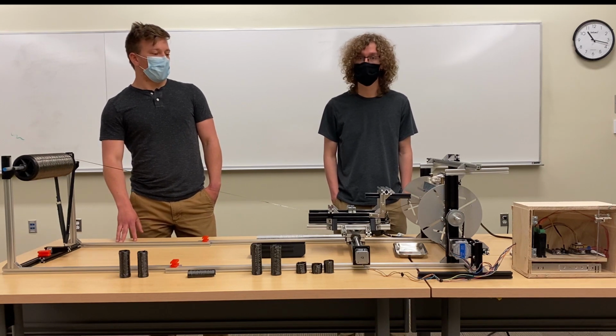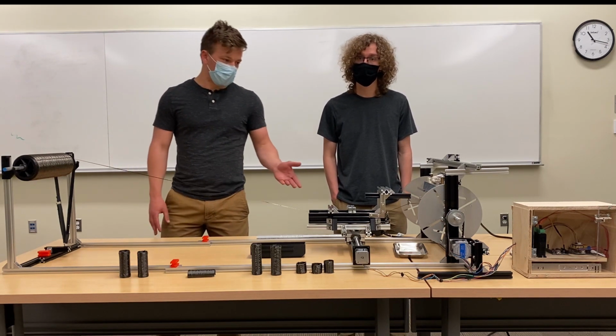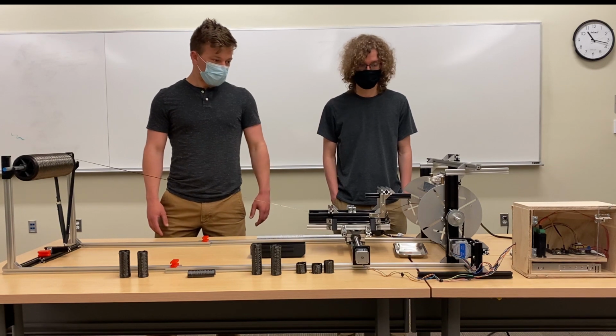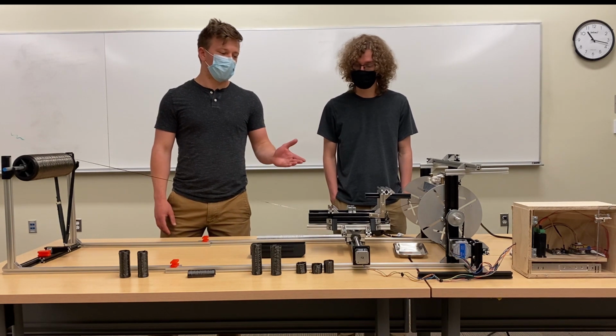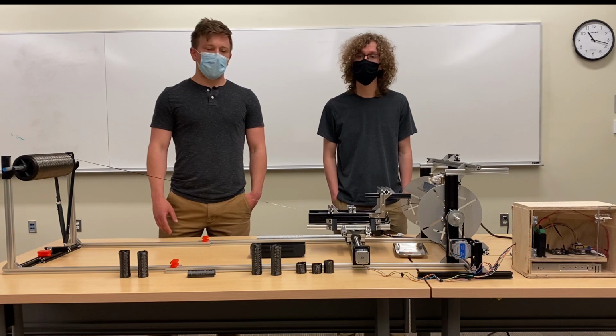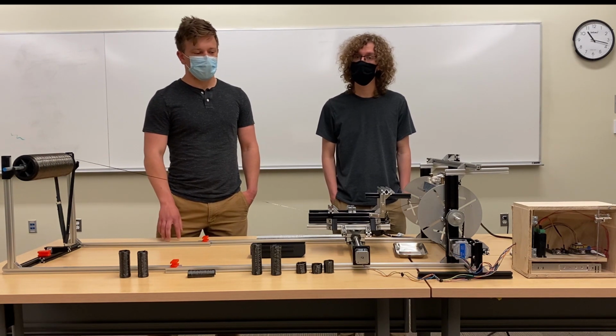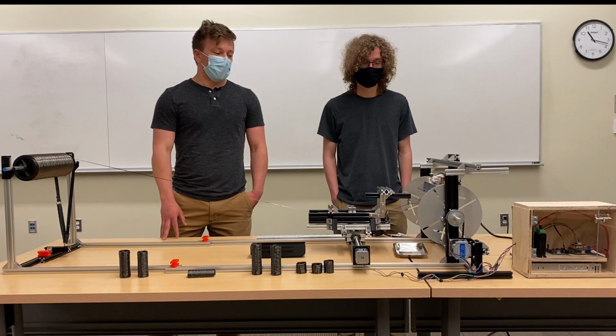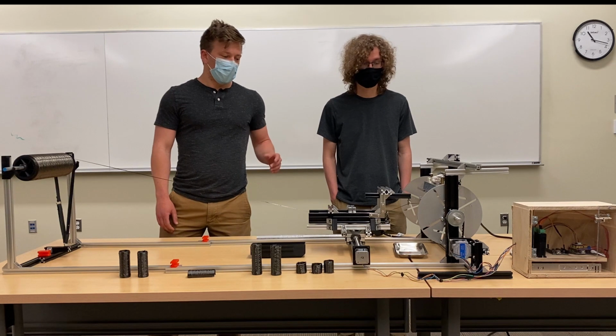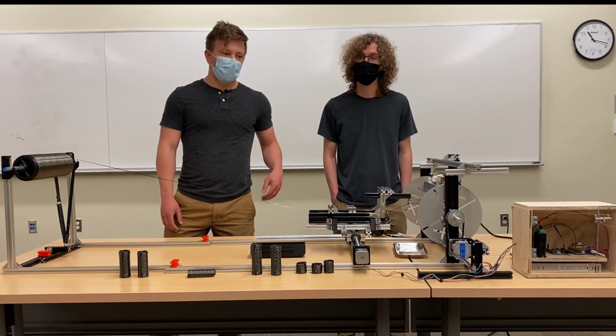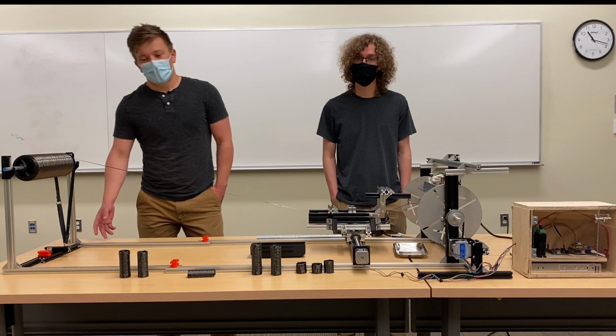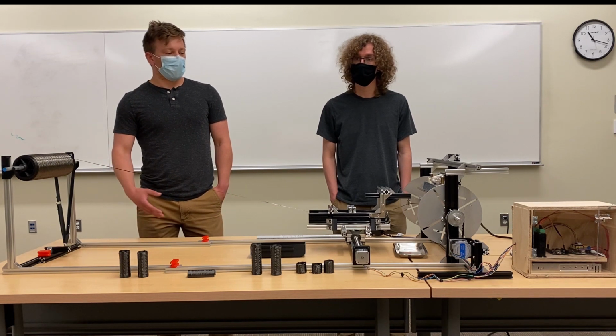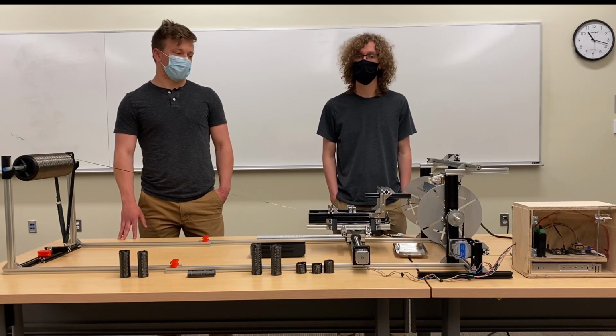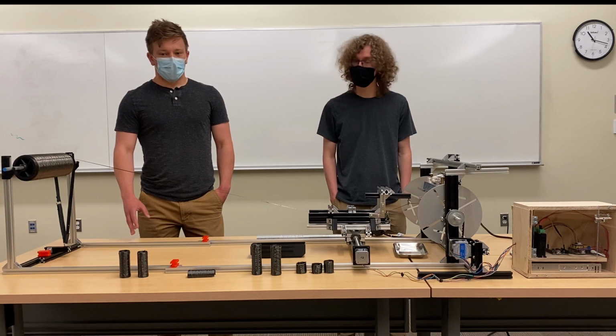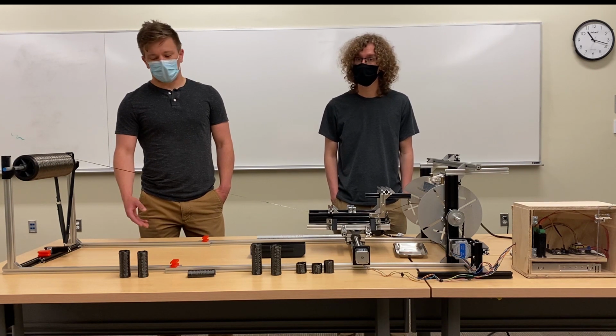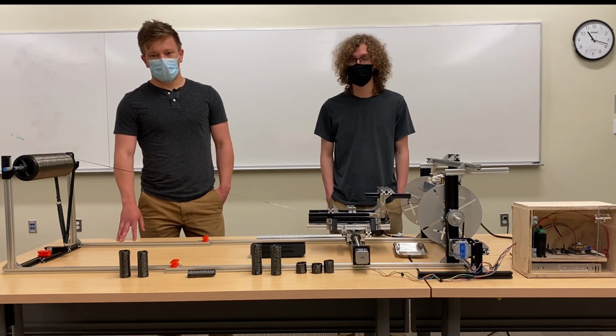We were also able to contrast these two different heating methods and found that the IR heater would be better suited for implementation into industry, as it is fully independent from the mandrel diameter, and it can be easily integrated into a lot of current winding mechanisms. It also allowed for significantly higher quality samples.